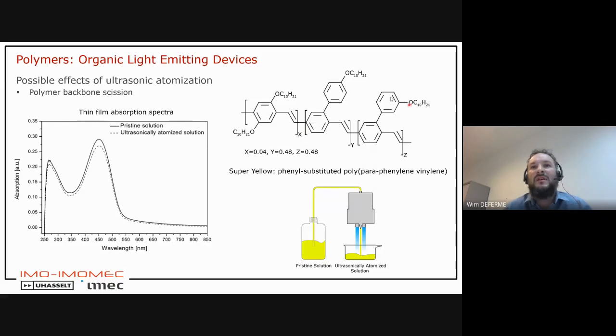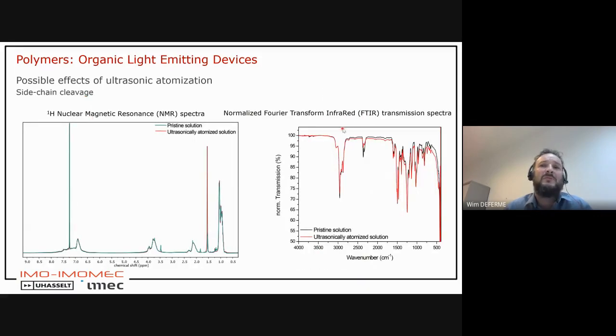So we took the specific polymer, this PPV, Super Yellow polymer, and we looked at whether we have cleavage of the backbone, or cleavage or scission of the side chains. So what we did, we ultrasonically spray coated our polymer, Super Yellow, and then looked, for example, in absorption to see if we have scission in the polymer backbone. We did some NMR and some FTIR measurements to compare the pristine solution, which is spin coated, and the ultrasonically vibrated system. Do we have some side chains that are cleaved off? But we couldn't find any change in the polymer composition, so that made us conclude that these ultrasonic vibrations do not have much impact on the polymer composition, probably because you have it in a specific ink formulation and not only the polymer itself.